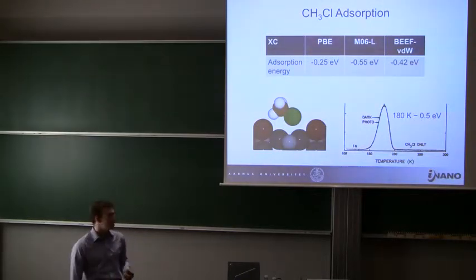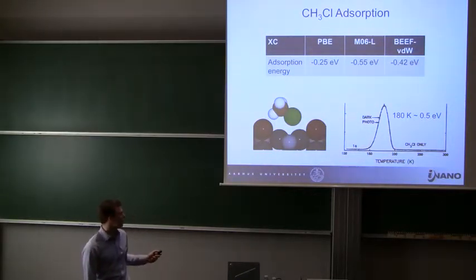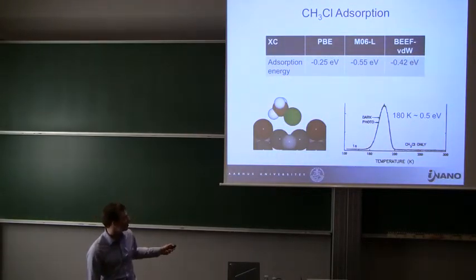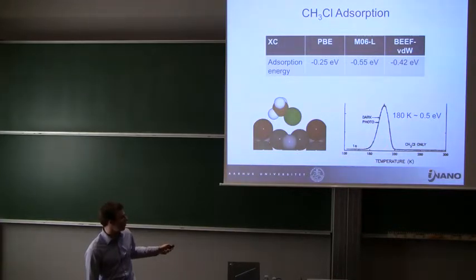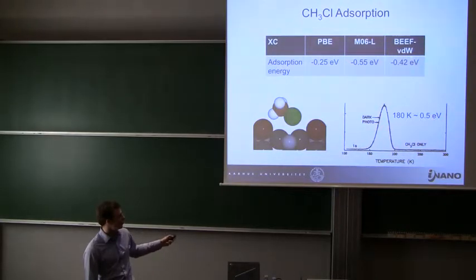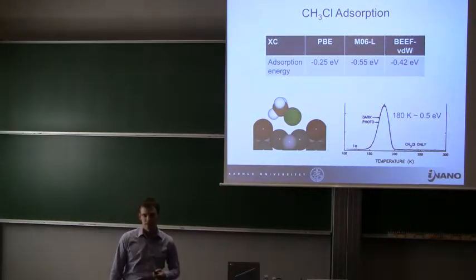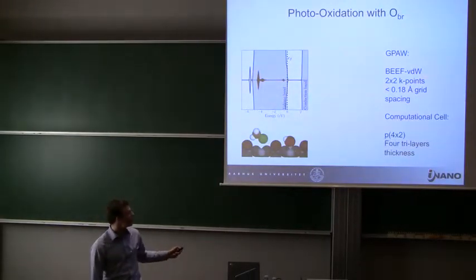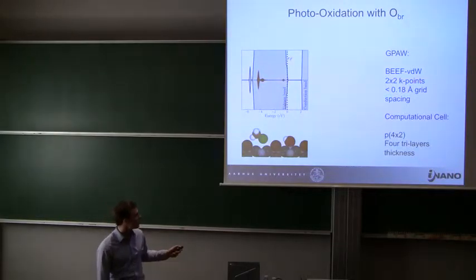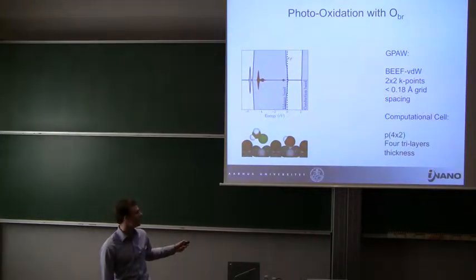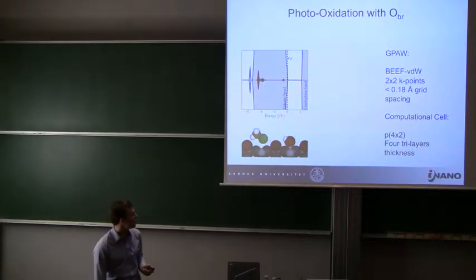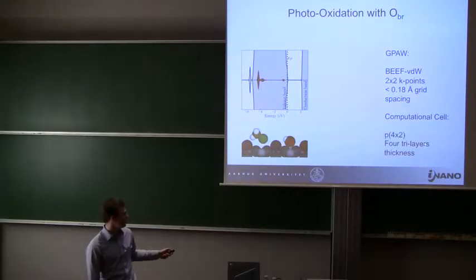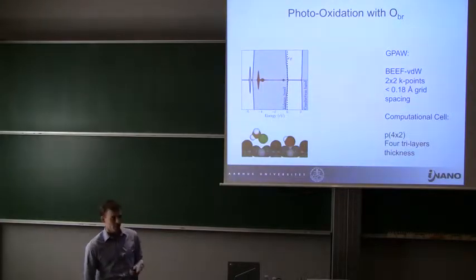But in a second I want to transfer this proton down to the oxygen, which means making a lot of reactive species. I am probably not the only one who knows that M06L can be very difficult to converge, especially when we have a lot of not so stable species. So it actually turned out that it was completely impossible to investigate this reaction with M06L. We were quite pleased that we had just discovered that the van der Waals functional had been implemented that we could now use and which converged reasonably for these kinds of problems.